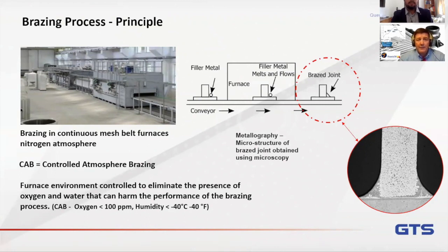Correct. So in the CAB furnace, we're trying to remove both oxygen and water to avoid oxide formation on the part. But we're also going to be using flux technology to enable us to clean the aluminium surface itself and remove any residual oxide post degreasing operations.